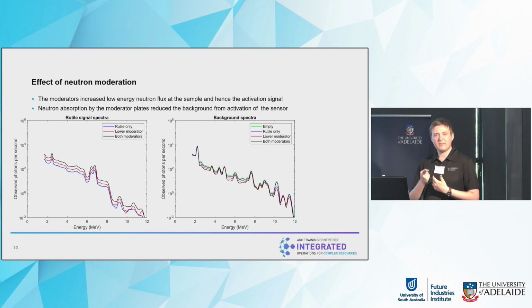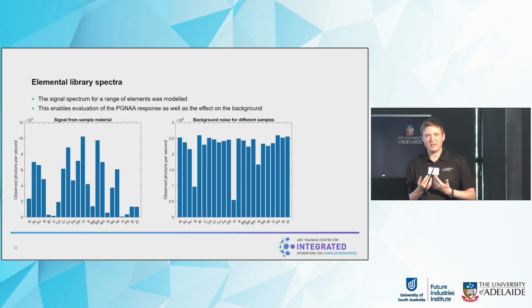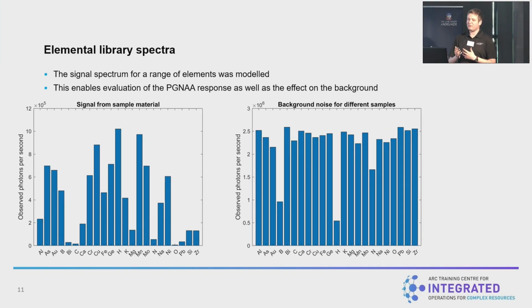There is another benefit: the absorption of neutrons within the moderator reduces the background, as shown on the right, where there's a consistent reduction, apart from the hydrogen peak at around 2 MeV and the carbon peak near 5 MeV, due to their presence within the moderating materials. So, as well as being able to test a wide range of characteristics, the simulation can also be used to help build elemental library spectra to help the analysis.